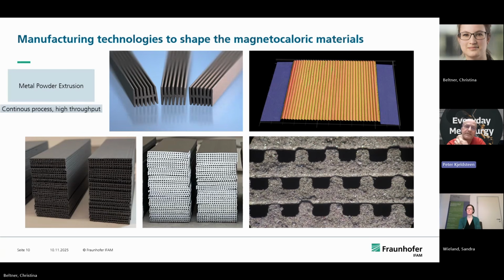The sintering and the heat treatment, is that done in one run, or is it two different? Yeah, this is basically done in one run. I mentioned it, that was my PhD topic, to find the temperatures and sintering times that match both the needs of the sintering, so the densification, and on the other hand the phase formation, because the temperatures are actually close where the densification and phase formation happen, but they are not the same. So usually the phase formation would need a little bit lower temperature range than the sintering needs. And that was part of my PhD to see how you can combine both to have it in one process.